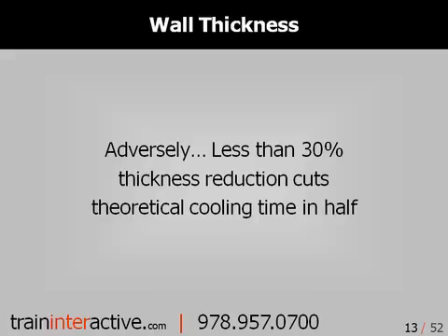Conversely, less than a 30% reduction in thickness will cut theoretical cooling time in half. In practice, the actual cooling time will decrease even more due to the improved heat transfer. Additionally, a part with reduced thickness will fill faster, require less packing, and consume less material, thus saving time, energy, and resources.